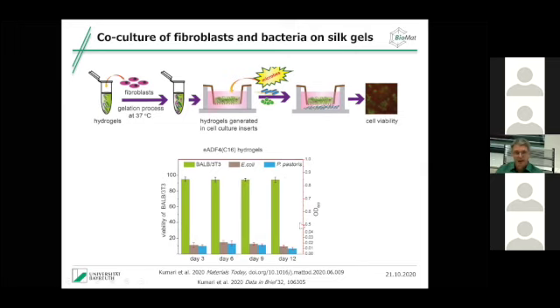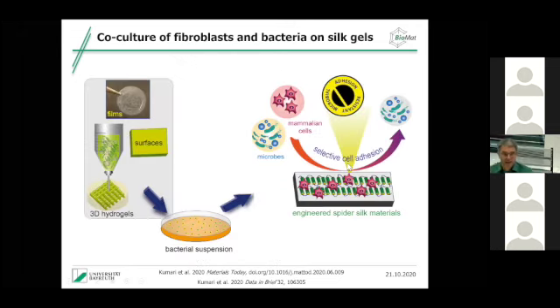And again, we have here an axis break, yeah? And look at these numbers. There's undetectable amounts of bacteria and yeast. So even in the hydrogel, this system works. What does that mean? Well, with spider silk, especially with the RGD variant, we now have a bioselective material that allows us to selectively grow cells on top and very selectively repel microbes. And we right now look at a lot of pathogenic relevant strands, multi-resistant strands, and so far we have not found any bacterium or yeast that can grow on the silk surface.